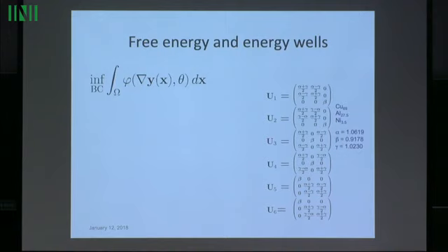And the symmetry theory that I didn't say much about, which tells you about the symmetries of this phi, says that if U1 is a minimizer of phi at some temperature, then automatically there are 6 such matrices, and there are these 6 matrices. As you can see, they're symmetry related. In fact, they're related by conjugation of rotations in the point group of a cubic crystal. But I don't want to go into so many details about symmetry. Those are the 6 matrices.